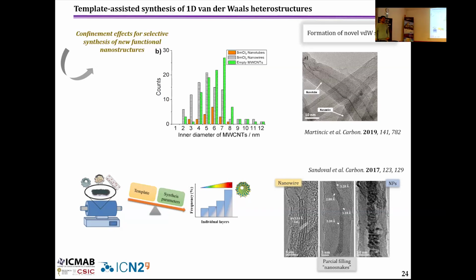This mostly depends on the amount of functional groups you have at the beginning. So if you have graphene oxide, with between 25–40% of oxygen, you have a high doping level. So it depends on the precursor you use. But in my opinion, it's more efficient than other doping techniques.